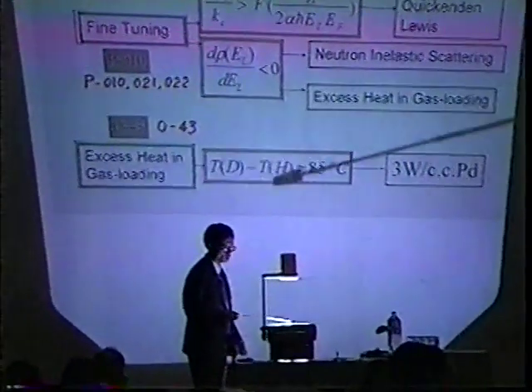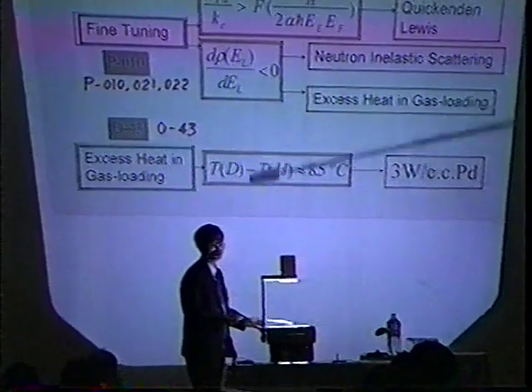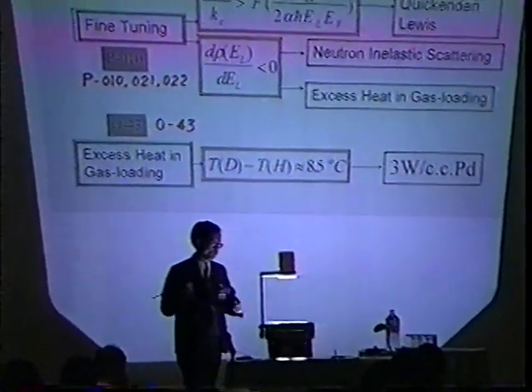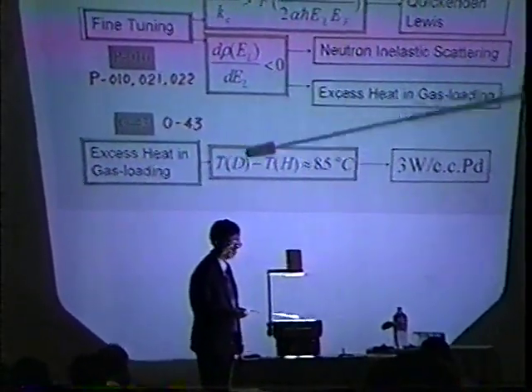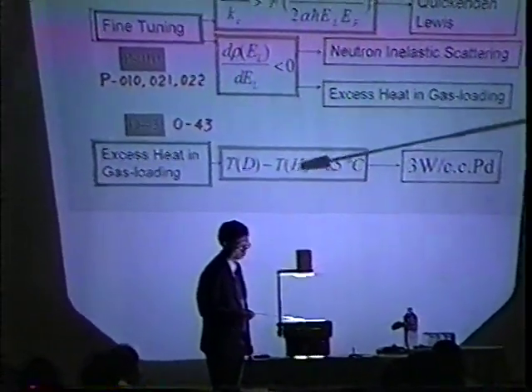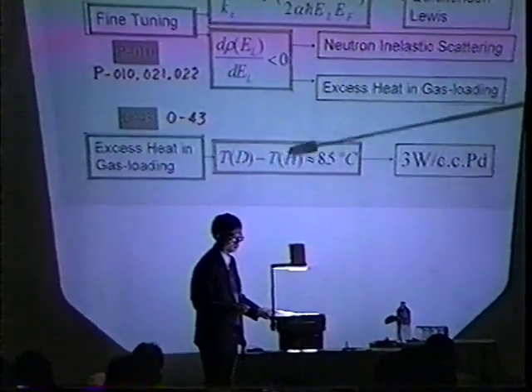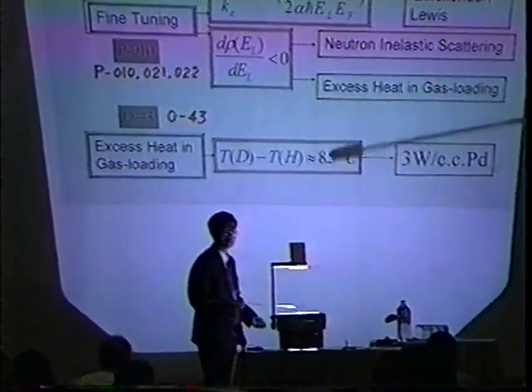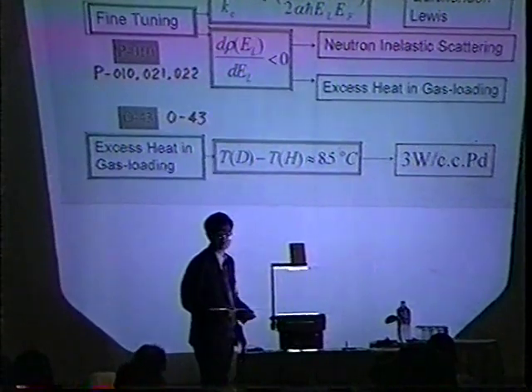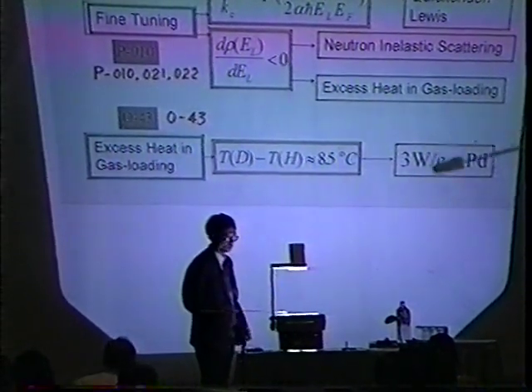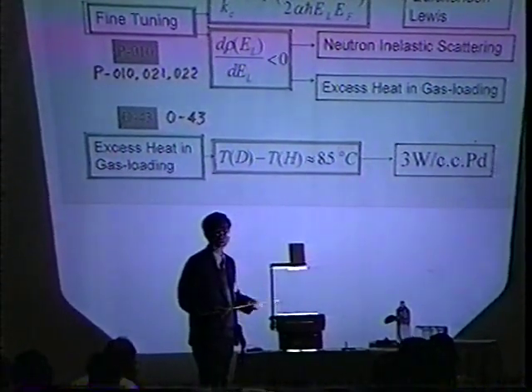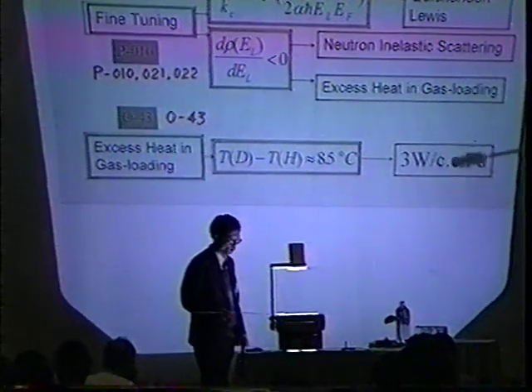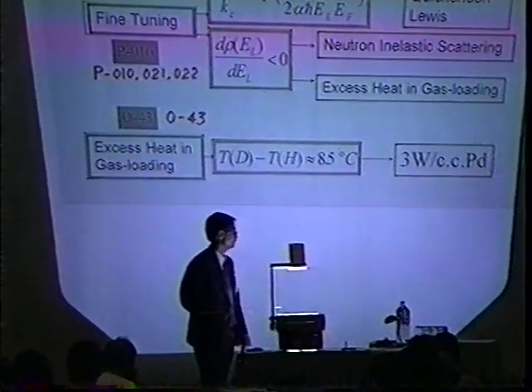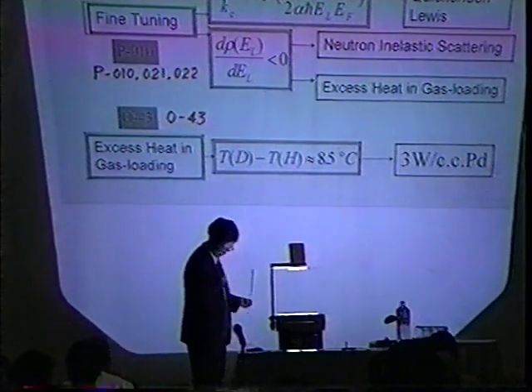This talk will tell you the temperature difference between the twin system. One is deuterium, one is hydrogen. The maximum temperature difference we measured is 85 centigrade. It's equivalent to about 3 watts of excess heat per cubic centimeter of palladium. Thank you.